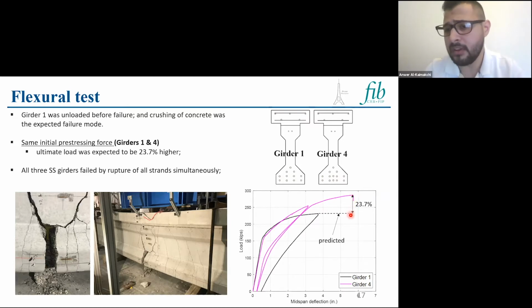And then we can see here that the load carrying capacity of the girder with stainless steel strands was 23.7% higher than that of the control girder. Girder 4 also failed due to rupture of the stainless steel strands. We can see here that all of them broke at failure, while the concrete in the compression zone was still intact.